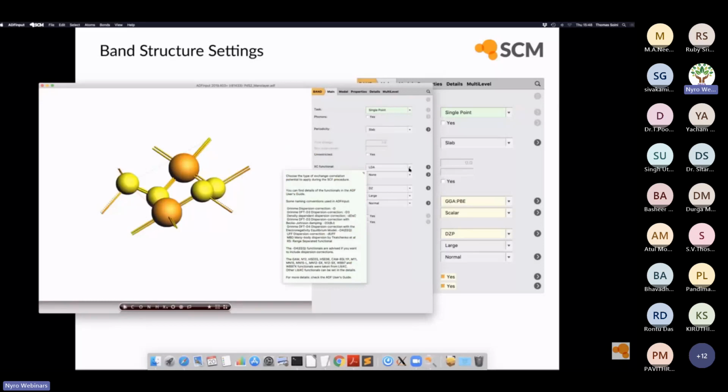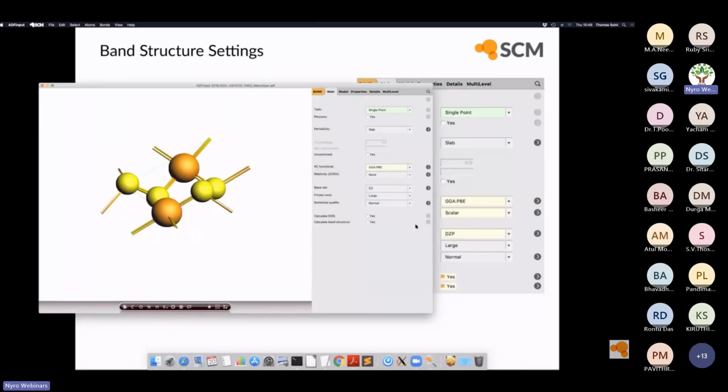And next we have to select our density functional description. For the present purpose, I just picked the PBE functional because it's reasonably universal and still delivers a reasonably good description. And we saw the warning already a couple of times. Indeed, this system includes heavy atoms, especially the palladium atom, and for that, a scalar relativistic description is at least advisable.